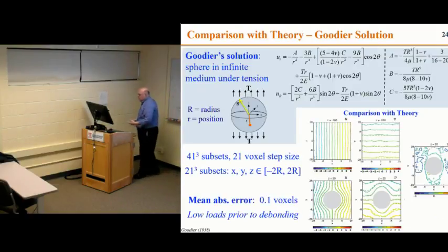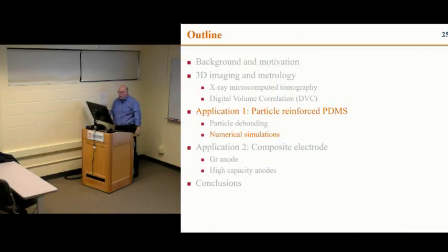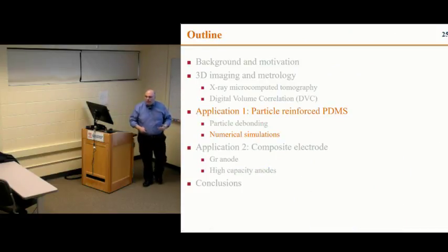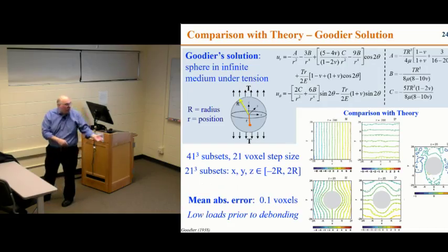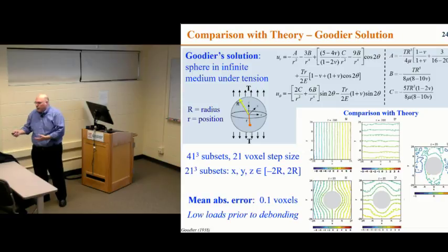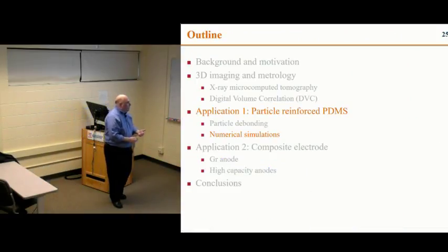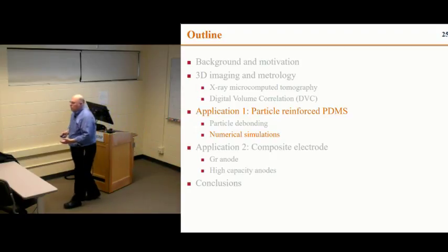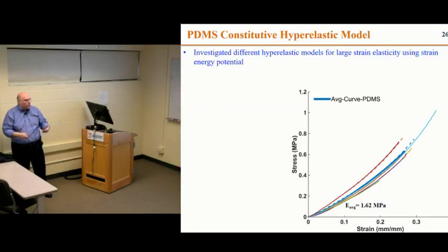So this was very encouraging, and basically was, for me at least, what convinced me that, okay, things are working, right? The problem is that this doesn't work once debonding starts. And in fact, if we make this comparison once debonding starts, the contours don't lie on top of each other. But that's the case that we would like to study. This is the important case in things like propellants, like asphalt, concrete, and so on. What you want to see is how the response or how the strength of this composite evolves as these particles start debonding. And the more particles there are, the more they would debond.